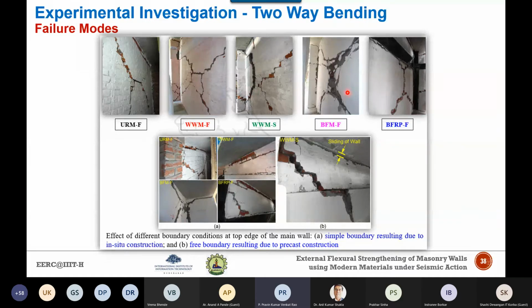Now in case of the basalt fiber mesh, the wall strengthened using basalt fiber mesh has developed its full capacity, and the failure showed the rupture of the fiber mesh. And here in case of the wall tested with the BFRP condition, especially at the top edge, the last course of the brick acted monolithically with the RCC slab during the out of plane bending. As a result, the horizontal cracks have been